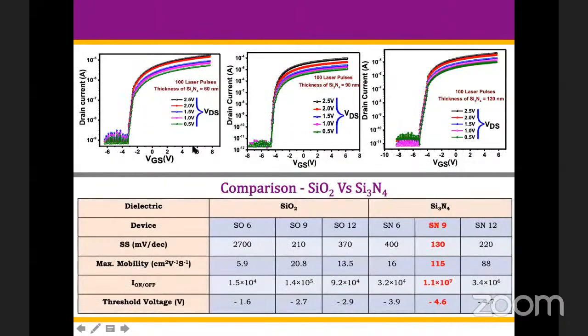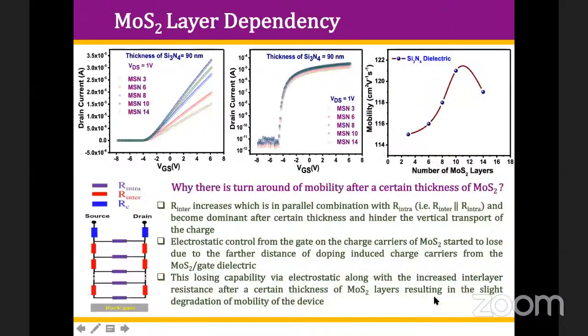characteristics are there. And these are the semi-log graph, and these are the parameters with silicon nitride, which gives better results even as compared to the silicon dioxide. So silicon nitride seems to be a good passivation layer in the transistor, and 90 nanometer thickness was found to be the optimum in this case.